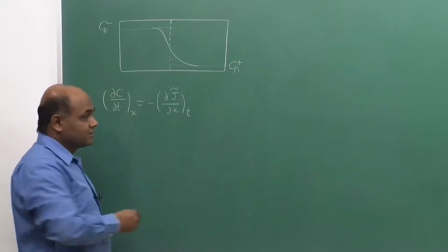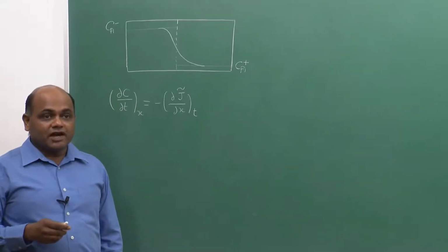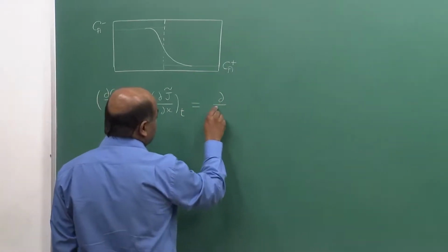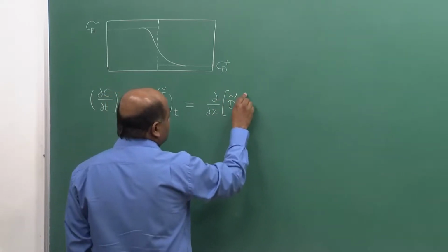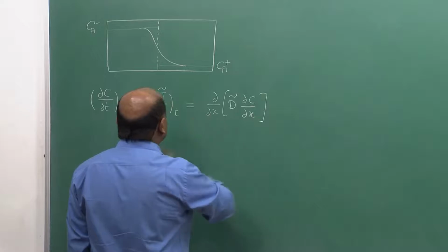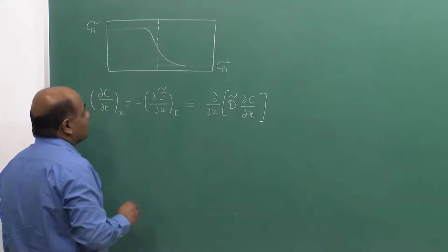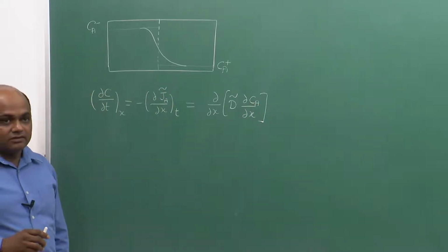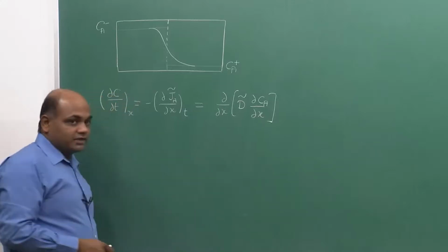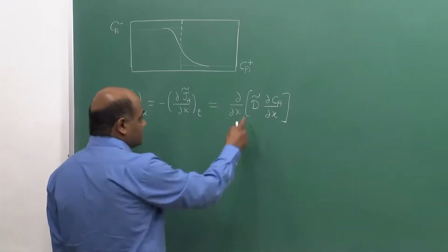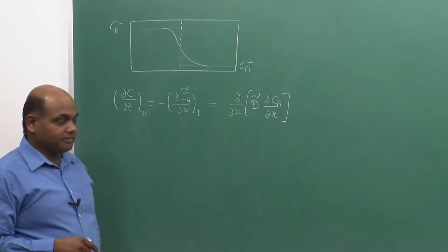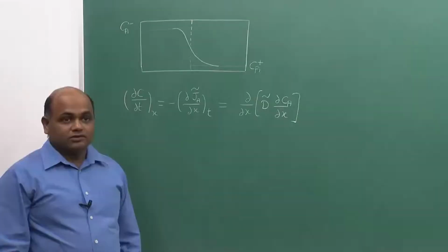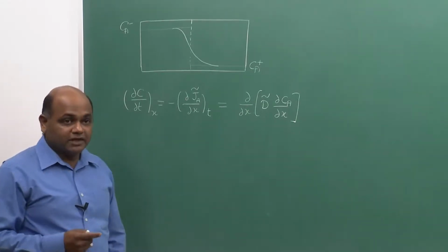and when we are considering the practical system, the interdiffusion coefficient D tilde is a function of composition, and so we have to write this right hand side as dou by dou x of D tilde times dou C by dou x, and since we are referring to component A, let us call this J A tilde and C A. Of course, we are referring to the binary interdiffusion here, which needs only one interdiffusion coefficient for both component A and B. We need to solve this equation for D tilde, and D tilde is varying with x. So, we will use the approach proposed by Boltzmann here.